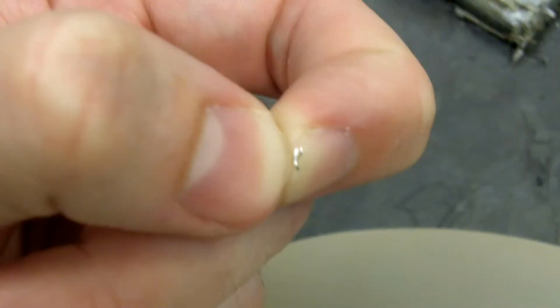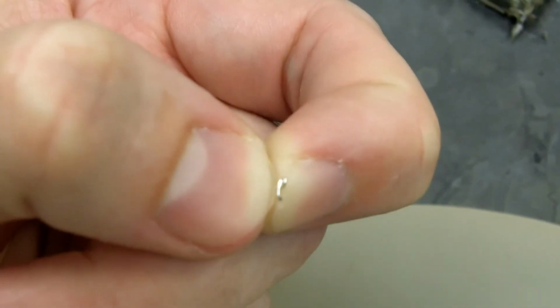Maybe the top layer is super thin and I just didn't polish the surface of the sample well enough to see it. Well, I'm far too lazy to polish this sample anymore, so let's do this. I'm going to take another link off this chain and sand off the surface just a little bit. So when we put it back in the microscope and we see an area with something missing, we know that that something that's missing is what was on the surface.